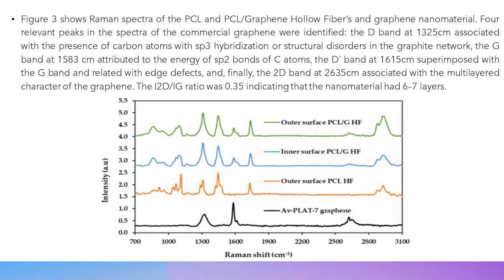Here in Figure 3, it shows the Raman spectra of the PCL and PCL graphene hollow fibers and graphene nanomaterial. Four relevant peaks in the spectra of the commercial graphene were identified. The D band at 1,325 cm⁻¹ associated with the presence of carbon atoms with sp3 hybridization or structural disorder in the graphene network. The G band at 1,583 cm⁻¹ attributed to the energy of sp2 bonds of C atoms.